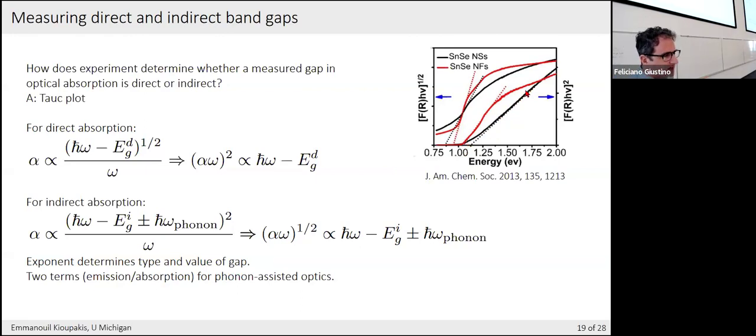So you see, when you look at the direct spectrum, this Urbach tail gets suppressed. But if you take the same spectrum and just process it, you see this Urbach tail becomes more prominent. And so in materials which are very defective, it's hard to measure the bandgap because these tails tend to be very, very long and very strong. So in this case, it's harder to see the bandgap. Maybe in this case, there are lots of defects that hide the onset.